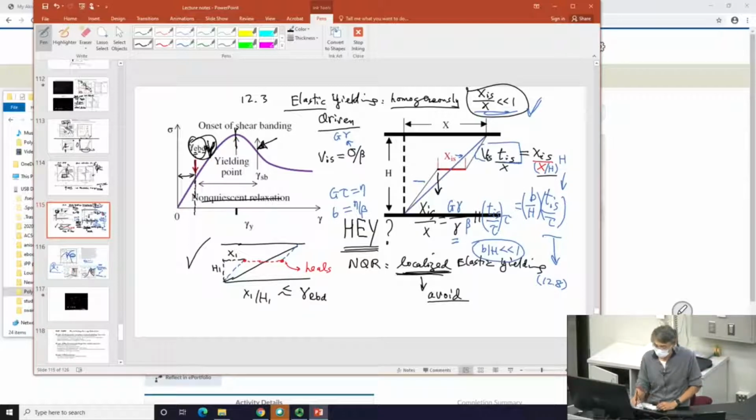Meaning, let's say it breaks up at a strain of 2, whereas if you don't stop, you have to shear until it's a strain of 5. So the termination of shear actually induced the failure to occur, quote unquote, earlier, meaning it required less strain for the failure to occur. And it occurs in absence of any ongoing deformation. So it's absolutely peculiar and difficult to understand to begin with.